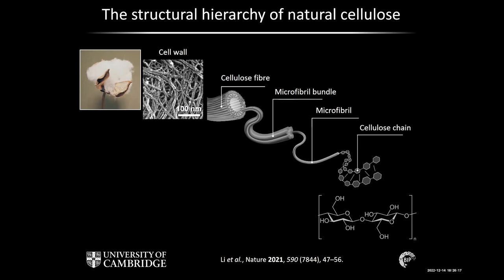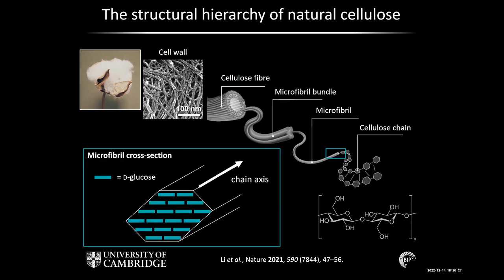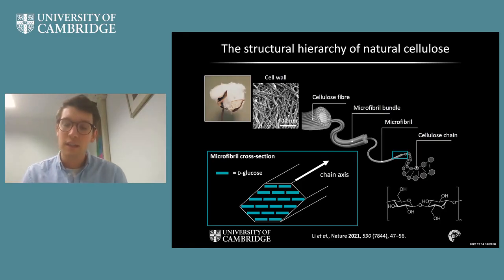And the perhaps slightly surprising thing here is that if we look more carefully at the cross-section of these microfibrils, we find that the cellulose actually forms a crystalline structure. So we actually have individual chains of D-glucose, the individual cellulose chains, stacked together into a regular configuration. And actually, this is really essential for the mechanical strength of cellulose, which is why plants like to use this as a material, but it also leads to interesting optical properties such as birefringence, which we can exploit in order to create the colorful effects that we want to achieve.